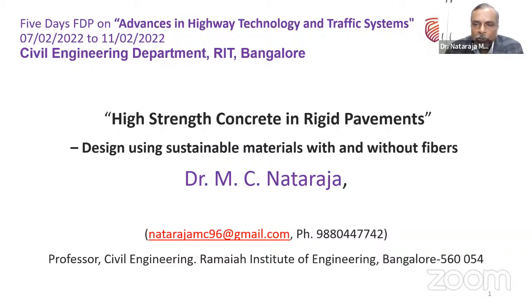And I have not seen any pavement application where concrete of strength more than M60 has been used. So probably M40, M50, M60 may be regarded as reasonably high strength concretes. But if you see the current code, IS 10262:2019, the actual high strength concrete starts from M65, having a strength of 65 Newton per mm square at 28 days, and going up to M100.